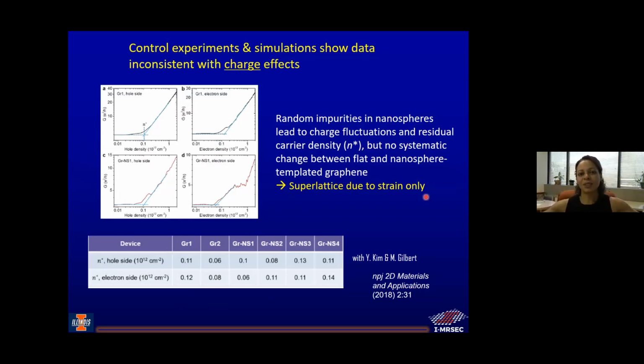However, the key word is random impurities, because impurities on top of these would have random magnitudes. And you can show that these sort of charge fluctuations and residual carrier density don't lead to any sort of superlattice effect like we saw. Now, they could see this in their calculations. We also did the control experiment where we took graphene and we spun nanoparticles on top of it, right? Because if there's a charge variation, then the charge difference should be there with the nanoparticles on top of the graphene or the graphene on top of the nanoparticles. It shouldn't matter. But when we put the graphene below the nanoparticles, we didn't see any superlattice effect. When we put the graphene on top of the nanoparticles, we saw a strong superlattice effect. So again, all of this implied to us that our superlattice is by and large due to strain, which is one of the first examples of a strain superlattice.